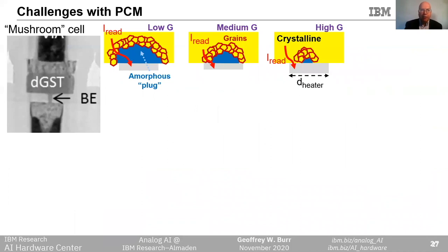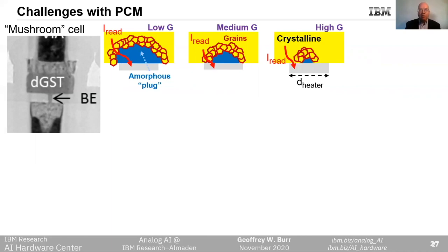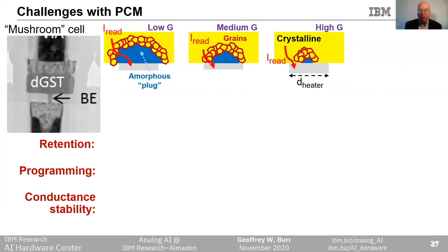The engineering trick is fabricating all the PCM devices at exactly the same size as we make them small. Even as we are getting good at that, there are real challenges for retention, programming error, and conductance stability — all related in some way to polycrystalline grains. In the prototypical mushroom cell, the high current density as read current travels from the large top electrode to the narrow bottom electrode — also known as a heater — creates a hemispherical dome of hot material. If this material goes over the melting point, around 600 degrees Celsius, and then quenches to room temperature fast enough, we block all paths for read current with a resistive amorphous plug, leading to a conductance value close to zero. To have complete analog tunability, we need intermediate states where read current makes its way through regions with numerous small polycrystalline grains, and these grains have an impact on retention, programming, and conductance stability.